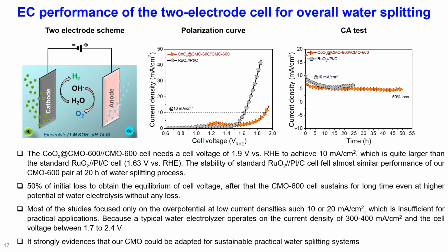Most of the studies are focused only on the overpotential at very low current densities like 10 or 20 milliampere per centimeter square, which is insufficient for practical applications, because the typical water electrolyzer operates at a current density of 300 to 400 milliampere per centimeter square and a cell voltage between 1.7 to 2.4 volt. It strongly evidences that our CMO could be adapted for sustainable practical water splitting systems.